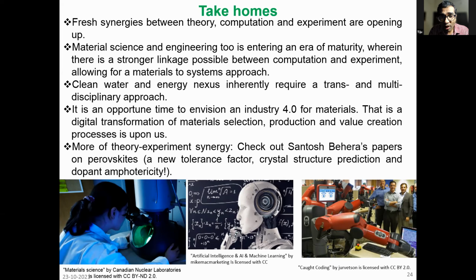And for more about the theory experiment synergy that has come out of the group, I would invite you to look at Santosh Behera's thesis. He recently defended his PhD. In fact, his PhD resulted in a new tolerance factor for perovskites. Very exciting, because this new tolerance factor actually helps you predict whether there are certain distortions that are possible, and hence requires you to do fewer experiments. It's no longer going to be hit and trial as we go forward. Secondly, he was also able to show crystal structure prediction.